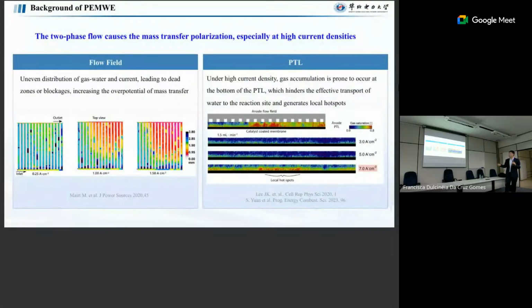And here, normally, because we have a heavy reaction, we will have a higher temperature. Then we have a little bit of convection. The convection effect can remove a little bit of bubbles, but this effect is not evident. The reason is that you have a compact system. For the catalyst layer, normally we have a pore size of a few 100 nanometers to a few microns. But for the PTL, we have about 50 microns. For the channels, we have roughly 1 millimeter. Inside, we have different sizes of transport. It's very difficult to meet all the requirements for the structures.